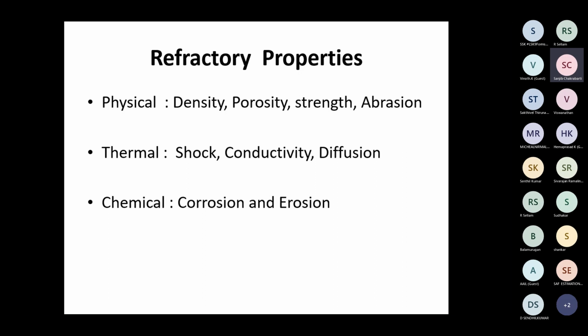Where density is a factor, porosity is also there. Porous refractory is only for insulation purposes, on the outside of the cylindrical surface. Strength means it is quite strong. The abrasive strength is quite high, and we call it compressive strength. The refractory doesn't have much tensile strength. There may be a little bit. There should be some flexural rigidity to avoid bending, but the tensile strength is very poor.